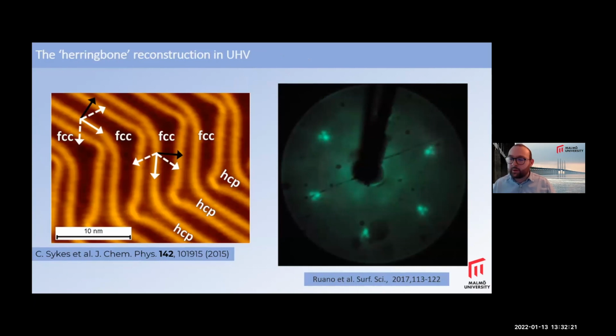So back onto this gold surface. It's well known that the gold surface has this so-called herringbone reconstruction, where you have this transition from FCC to HCP domains, and then you have these stripes that separate this transition. And because you have free rotated domains, you get these shoulders, which give it sort of this typical herringbone pattern.